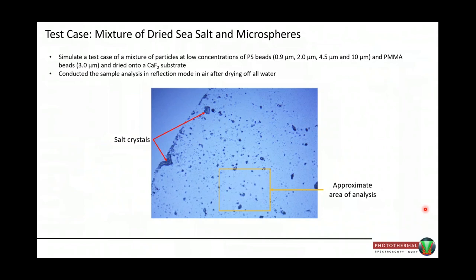This is related to the bioplastics discussion that Asao will go into later, but these days microplastics are appearing all over the place in the environment. And this is a simple test case where we took some salt crystals and mixed in some polystyrene beads and PMMA beads. The polystyrene beads were 1 micron, 2 microns, 4.5 and 10 microns, and the PMMA beads were 3 microns. And we dried them onto a calcium fluoride substrate.